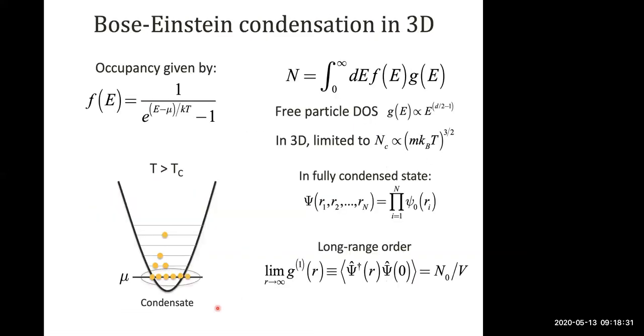And when you reach the lowest energy eigenstate, you form a condensate, and the chemical potential stays clamped near this energy. And the wave function of the fully condensed state would simply be some product state of every single particle in this lowest energy eigenstate. Another important feature of the condensate is the fact that beyond threshold, you have the appearance of off-diagonal long-range